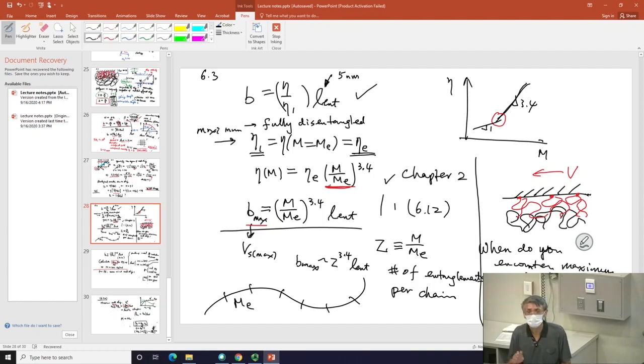However, I know I'm confusing you, but confusing you is the way for you to learn. However, keep in mind, eta 1 has a whole range of values possible. This is the mystery of it. In other words, it has to do with the degree of disentanglement you have. And unless you push it to maximum disentanglement, which we will talk about right after we finish this question, you would not know what is your B per se.